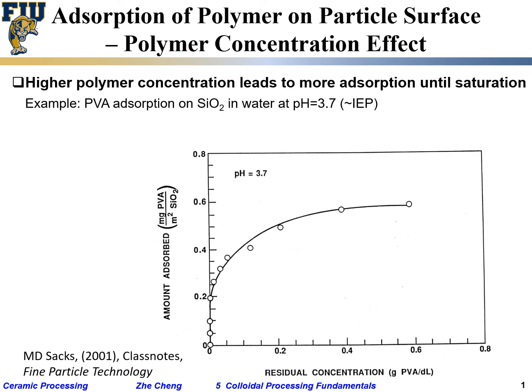But in reality, if that's the case, I'm going to show some actual data. This is showing the amount of polymer adsorbed. We are talking about PVA, a water-soluble polymer, onto silicon dioxide at a pH of 3.7, which is close to the so-called PZC or IEP, which means the surface charge is almost zero, which means I do not have help from electrostatic charge. I'm just seeing the polymer effect.